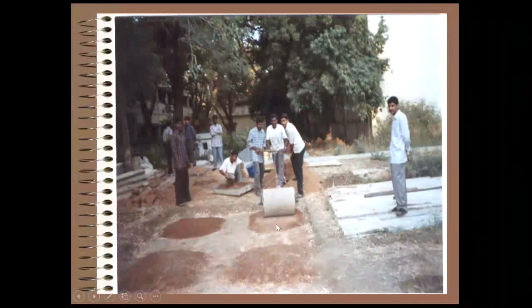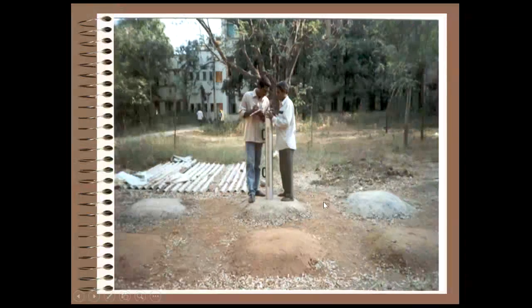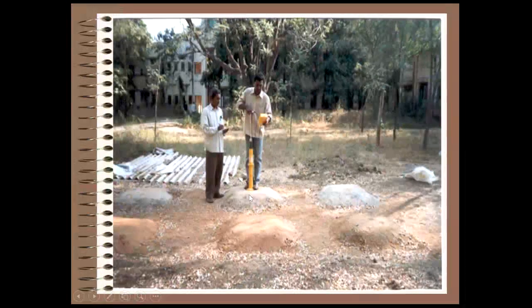Then these small stretches were constructed. As I told you, one side 6% cement is added to all the different types of morams, other side no stabilization. Like this, now ready, cemented and non-cemented. You see, after the setting time, we also measured the Young's modulus and instant CBR. This is a Loadman test to give the Young's modulus, and also Clegg impact. This gives the instant CBR value.